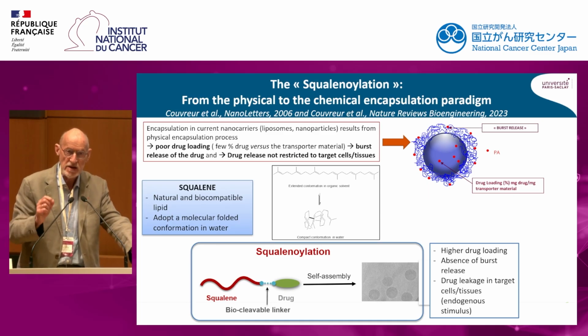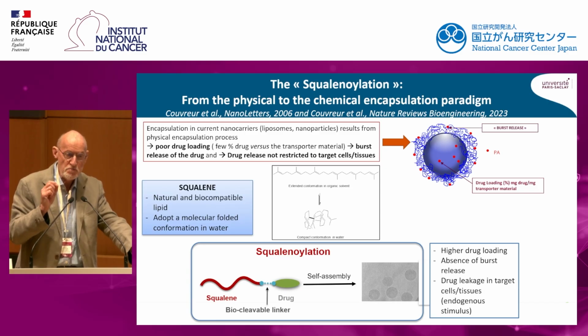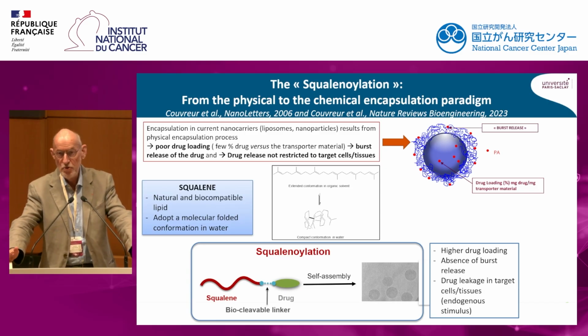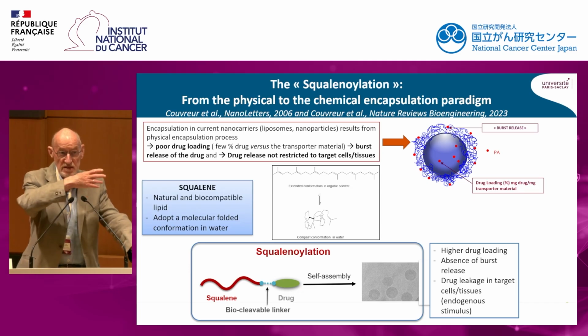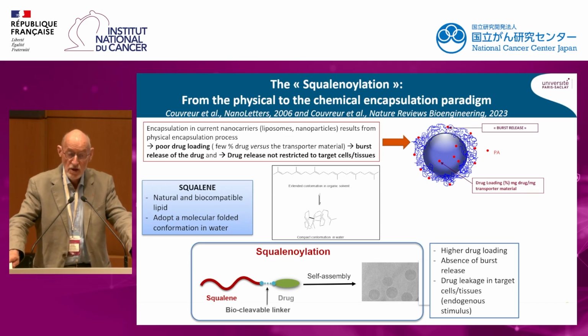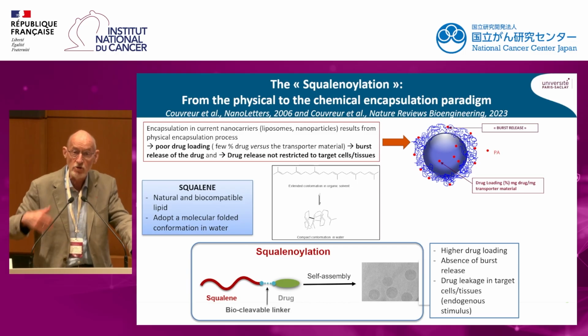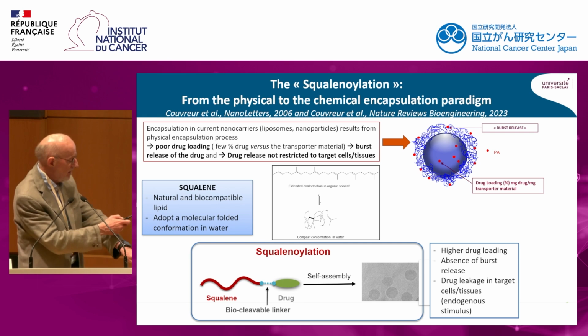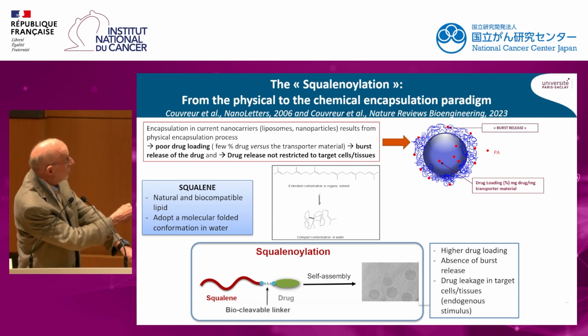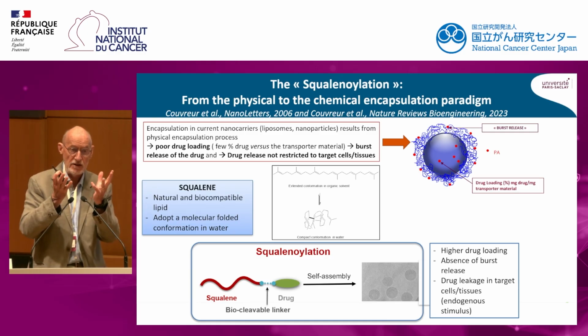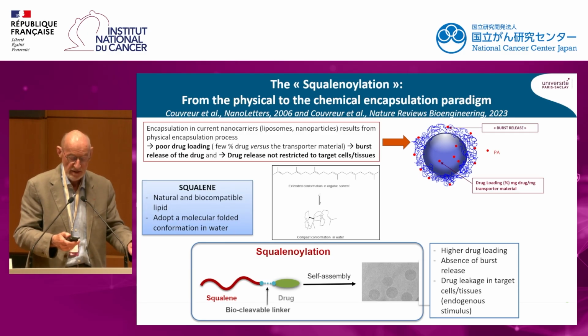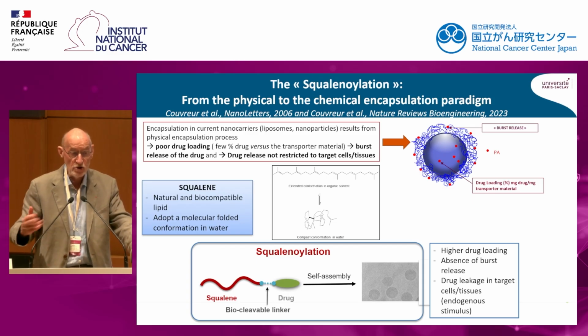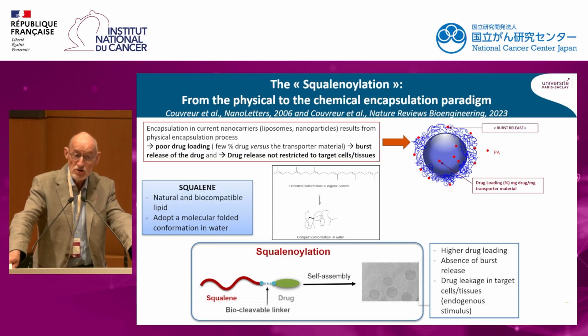This means, in weight, only a few percentage of the drug versus the weight of the transporter material, for instance, the polyalkyl cyanoacrylate polymer. The second limitation is a burst release, the uncontrolled burst release of the drug after intravenous administration. And this is due, as you can see here, to this fraction of the drug, which for thermodynamic reasons is rather adsorbed at the surface of the nanocarrier than really encapsulated into its core. And therefore, the third limitation is that the drug release is not restricted to the target cells or tissues.